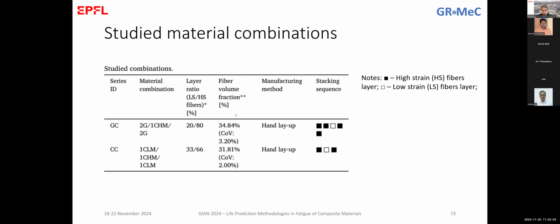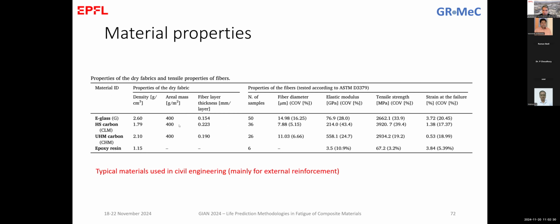Yeah, so only if there is a question, do not hesitate to interrupt me. So we did several material combinations, carbon and carbon. Carbon and carbon means layers of low modulus and high modulus mixing together. And then we also did combinations of glass and carbon with high modulus mixing together. We selected this high modulus exactly because of the difference of the strain. The high modulus is 0.5 strain at failure, glass is 3.7.